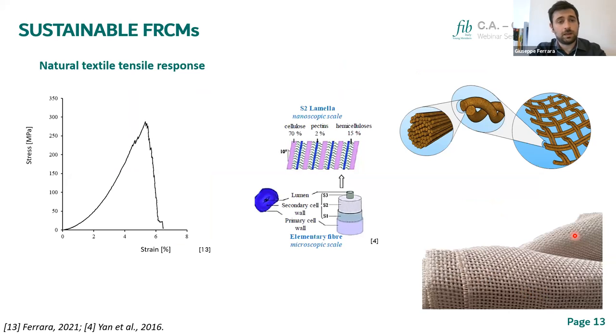Before introducing the sustainable FRCM mechanical behavior, I will just quickly spend a few words about the tensile response of natural fibers in general. Here we have a stress strain response of a flax textile test in tension. It is actually a quite linear response up to the rupture of the textile, but what we can observe is that at lower strain levels, we have a kind of lower stiffness of the system. This is due, of course, to the arrangement of the textile that is made by several threads, which are made by several filaments, not always working all together and contributing in the same way to the strength of the system. But also, on a nanoscopic scale, the parts called the walls of the single filaments are not really oriented in the tensile direction of the threads of the filaments, generating this kind of lower stiffness at lower strains. This is a significant aspect, because it significantly influences the overall mechanical behavior of the composites.